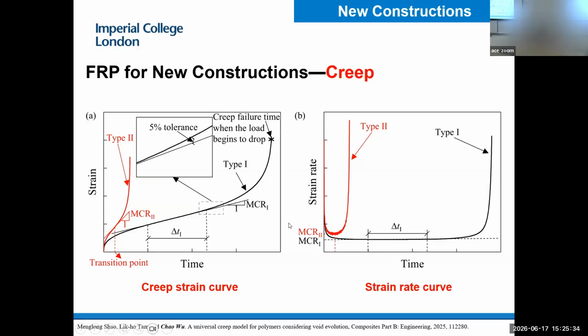Here I want to highlight this research on creep of FRP, because FRP has a resin matrix in it, and polymer resin is very sensitive to creep. That means under loading it will deform slowly, and eventually it will fracture even under a stress much smaller than the material strength. This is a typical creep behavior.